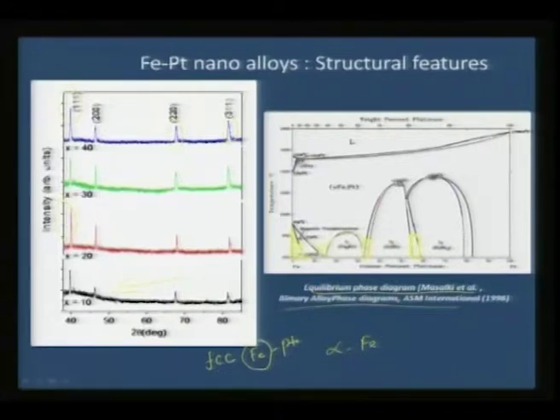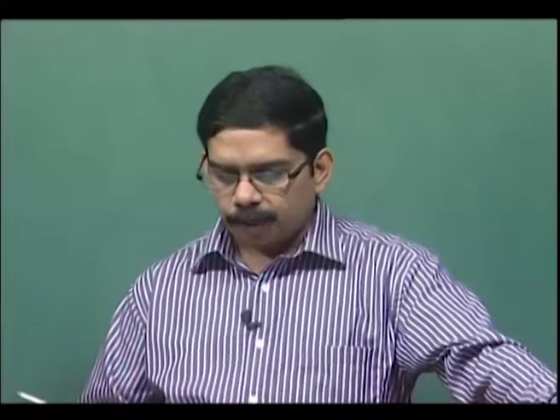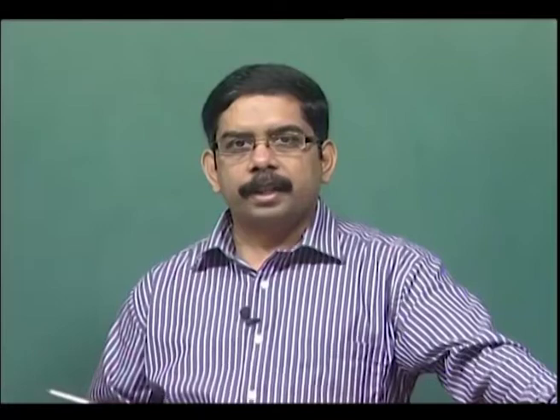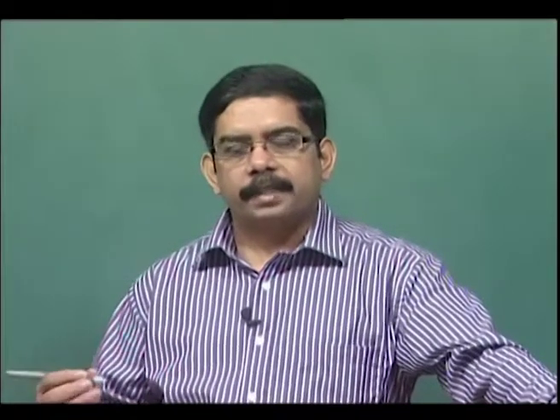But even at high temperature we are able to stabilize FCC iron, and this is because of not only the effect of platinum, but also the effect of sonochemistry, because even for undoped one we are able to stabilize FCC pattern. So the formation of metastable phase is one of the real trump cards of sonochemistry, mainly because you are able to get the as prepared powder which is amorphous in nature.